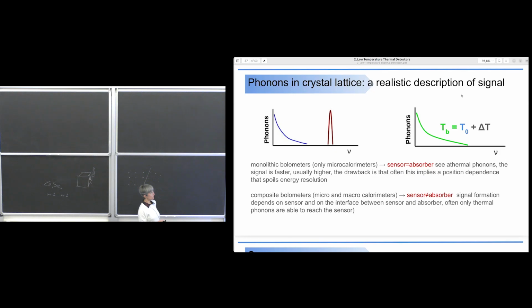And the motivation is that if you want to study this mechanism, you need a sensor that is sensitive to this, and then one that is sensitive to this. But whenever you add a sensor to your system, you also change the system. So the model is quite complicated. In any case, what happens is the following: you may have a kind of monolithic absorber, a monolithic bolometer where you are sensitive to athermal phonons, and therefore you can read out a very fast signal.